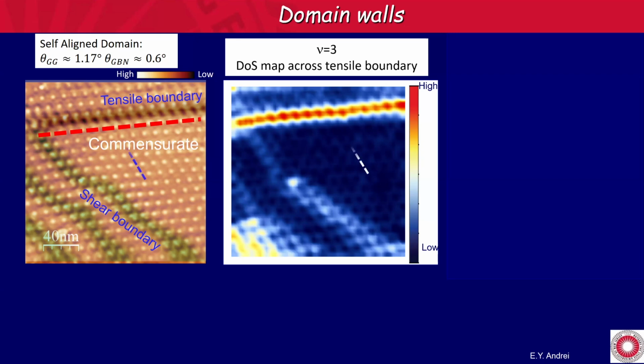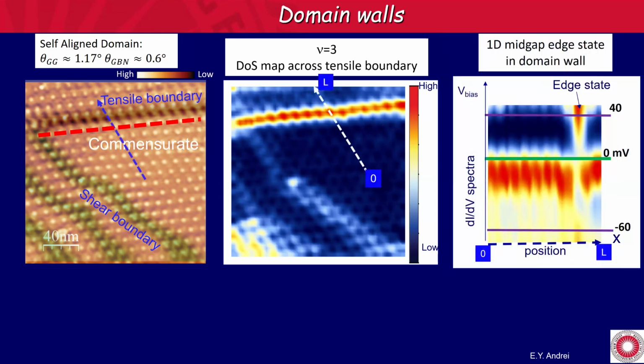And if you take spectra across this line, you see that when you cross this line, you get something that looks like a mid-gap state. Okay, we do not know yet what it is. We're still working on this. And this could be a candidate for those chiral edge states that give rise to the quantum anomalous Hall effect.